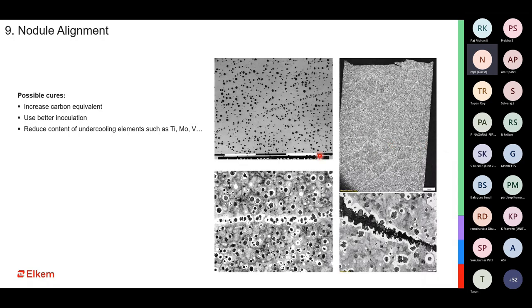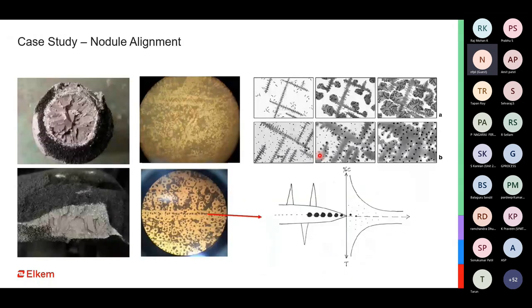One of the most common ways to solve it is by improving the inoculation. If you are able to improve inoculation, you restrict directional solidification. You do not allow graphite to precipitate next to the dendrites. You do not allow dendritic arms to be very long, allowing for graphite precipitation on its sides. And how do you do that? We do that, one, by better inoculation, and two, by ensuring that you do not have trace elements which are deleterious to graphitization. So these can be some of the ways to control or reduce nodule alignment.